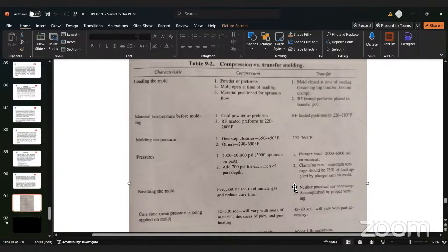Here, one rule is there: 700 psi for each inch of the part depth. This is one type of thumb rule. 700 pounds per square inch for each inch of the part depth. Here in this case, transfer molding clamping ram minimum tonnage should be 75% of the load applied by the plunger on the mold.